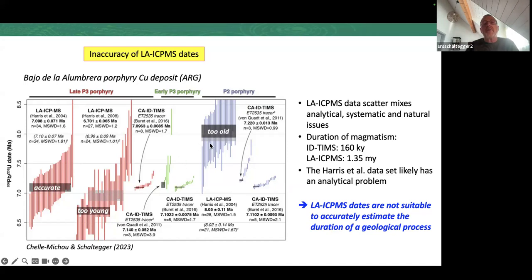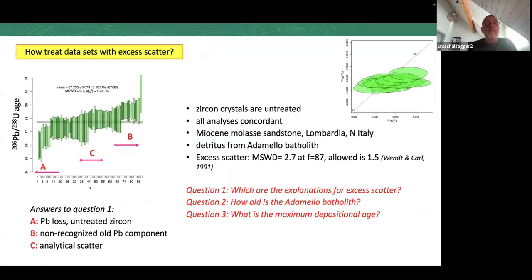And from the same lab, for the P2 porphyries, we have a statistically relevant data cluster, which is too old, because we also have chemical abrasion ID-TIMS dates here. My point is that the duration of magmatism which was calculated from the laser ablation dates is completely off, is an artifact of these analytical problems. The duration is probably something like 160,000 years and not 1.4 million years. So generally speaking, laser ablation dates are not suitable to accurately estimate the duration of a geological process. But now, this is also very negative, very pessimistic.